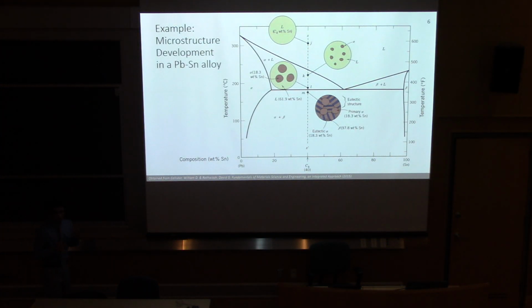And before I go into the single crystal synthesis, it might be useful to talk a little bit about the definition of flux growth. Over here, we are using a simplistic form of a tin-lead alloy phase diagram. We start at point J, which is entirely in the liquid phase. The tin and the lead are completely mixed together in the liquid phase. We then slowly cool it down to about 200 Celsius at point K, by which we have solid particles beginning to form in this liquid matrix. As we continue to cool slower and slower, the solid particles begin to get bigger and bigger, which is the premise that we want to have in crystal growth.